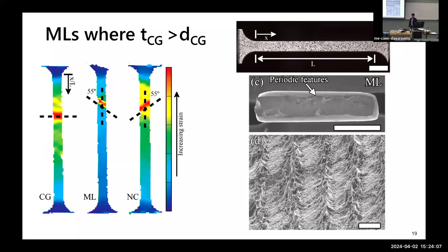When you look at the fractography, you see that being played out. You can see ductile failure mechanisms at different scales, associated with rupture of the nanocrystalline layer and ductile rupture and coalescence of voids in the polycrystalline layer. But these mechanisms are operating independently. So it's basically like we took two different materials and glued them together, and the layering isn't really doing anything. I could have taken a big piece of nanocrystalline material and a big piece of coarse grain material, glued them together, pulled it, and gotten almost the same result in terms of mechanical property outcome.